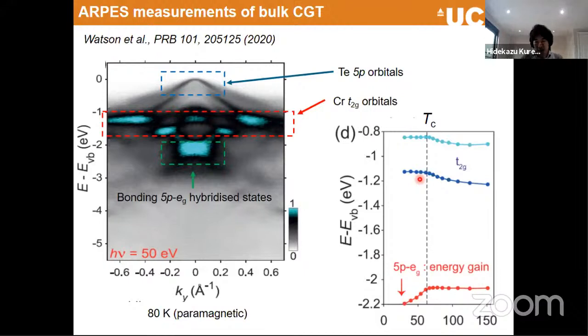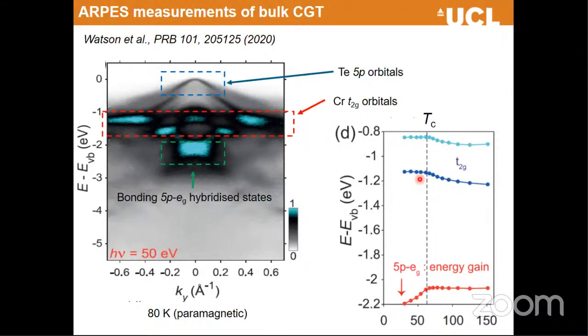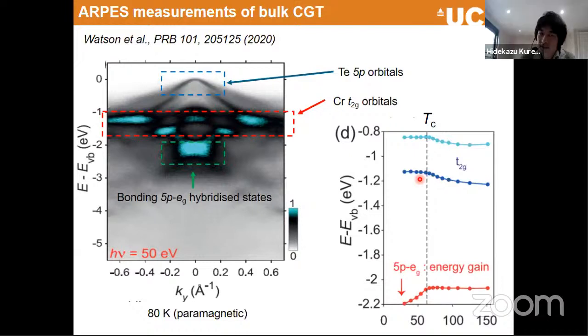Sorry, and by the way, looking at this, I just realized that I think I know what happens in your system. What happens is that you just screen out Hubbard U, and it becomes effectively smaller. And because your exchange coupling is inversely proportional to Hubbard U, by reducing Hubbard U by metallic screening, of course, you would increase your interaction. Okay, I take that.